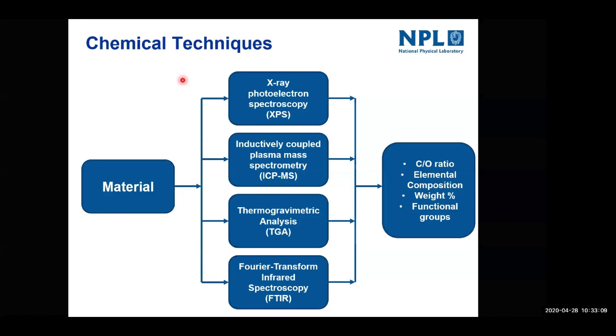And so this is very much a go-to technique, but at the same time, if you have highly functionalized graphene, FTIR is very powerful for understanding those functional groups in more detail. Other than just the carbon and oxygen ratios and bonding, you can get a better understanding of the functional groups that are present. And TGA, which is a bulk technique, essentially is heating up a material and seeing the weight lost with temperature. This gives you not just an idea of, say, moisture content, but an idea of the weight percentage of the chemistry as well. So that's, again, very complementary techniques to be used together to get a better understanding of the material.